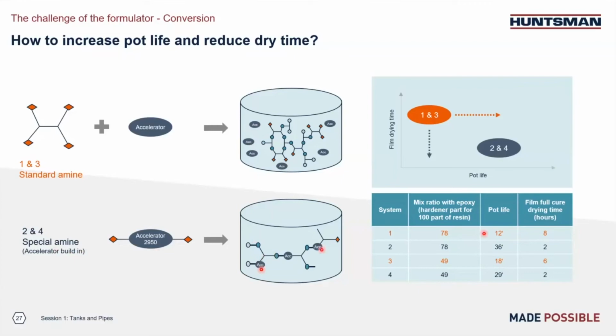So if we look at the table on the right side, we compare our special accelerator 2950 with industrial standard accelerators. For example, in system 1 and system 2, we both use the same mix ratio with the same epoxy resin, 78 parts with 100 parts resin. You can see with accelerator 2950, we can still have a pot life of 36 minutes versus only 12 minutes for the reference control, right? So we almost triple the pot life, but we can cure the system in 2 hours versus 8 hours. So we can cure much better, right? And you can see the similar change between the system comparisons 3 and 4.